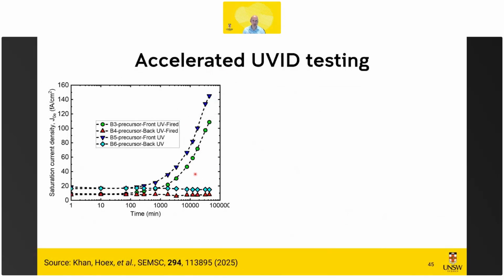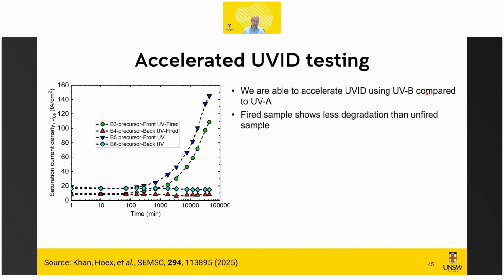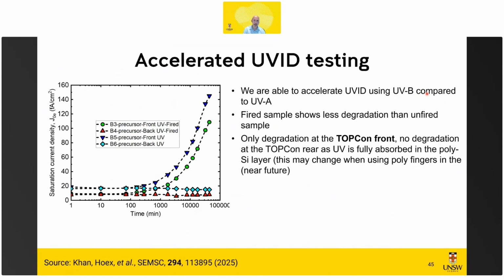This is work that we also showed earlier, so for UVID we were able to develop a rapid test that allows us to get feedback a lot quicker using UVB, which is a shorter wavelength UV. It's not triggering a new failure mode, it's just the same failure mode quicker. We see a difference between fired and unfired. I will not go into detail here, but that will help us unravel the mechanism. For TOPCon solar cells without polyfingers, you only see sensitivity on the front, not at the rear. When we have polyfingers, unfortunately, that will change.